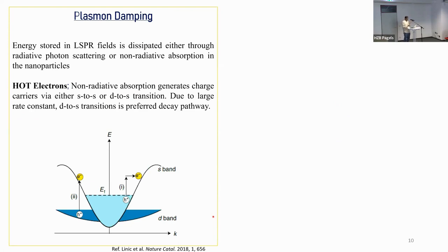And we know in a metallic nanoparticle, you have electrons at the Fermi level, right? And then what happens? Because of that energy damping, lots of electrons undergo excitation via the s-to-s or d-to-s transition, and you form these excited electrons, which are called hot electrons in this field. And these excited electrons, which are above the Fermi level, can then be injected. These hot electrons can be injected into the CO2, make CO2 really reactive and convert it into useful chemicals.